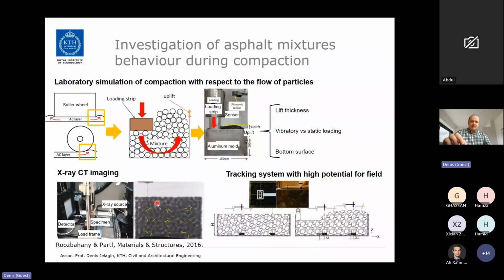Let me see if I can start the movie. Basically, what we did, we used modeling material. Let's see, maybe I should turn off pointer first. Yes. So we used modeling material, kind of representation of asphalt mixture composed of glass beads, and some of those glass beads had steel wire integrated inside, so something which is easy to track. And that allows us to quantify both vertical but also lateral deformation in the material during the test.